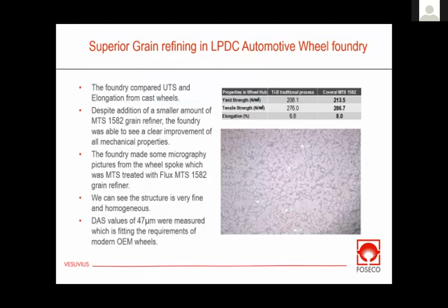This is where we saw some very interesting things. The average elongation they had on the wheels using their traditional tibore master alloy process is 6.6%. In all the wheels done with our new MTS 1582 process, the elongation jumped up to 8%. So even though they are within specification, they saw an improvement in the mechanical property of elongation, which is critical for wheel foundries.